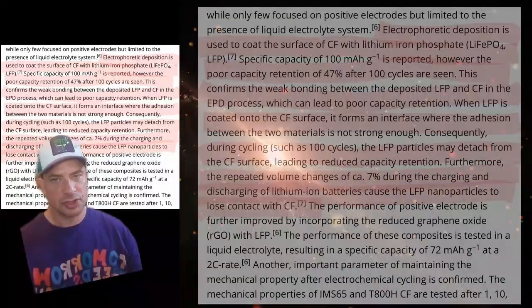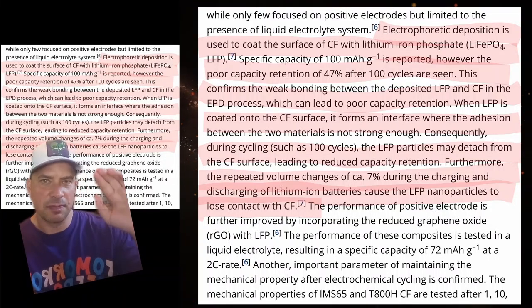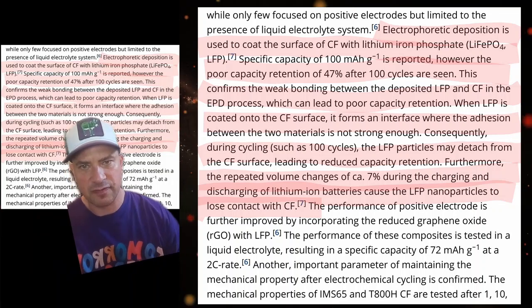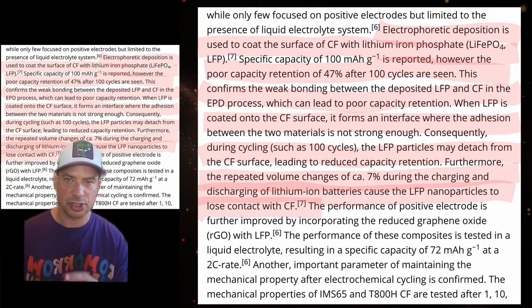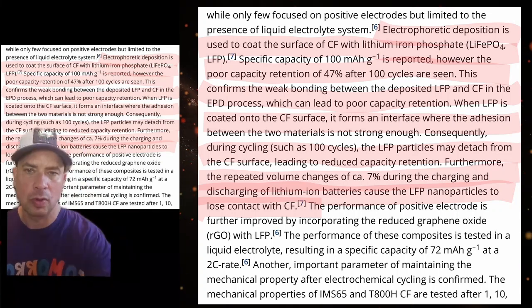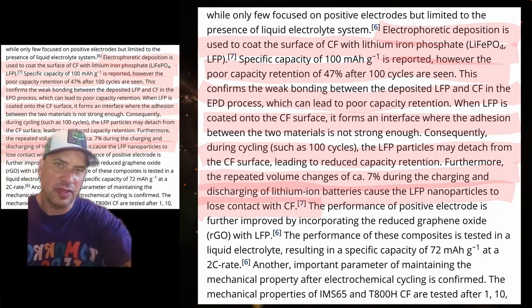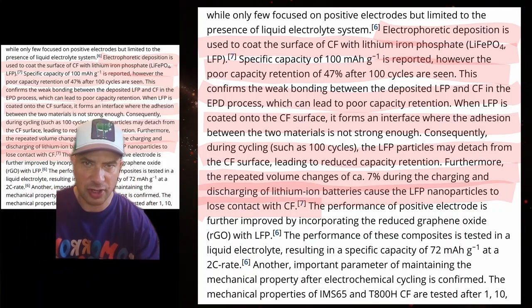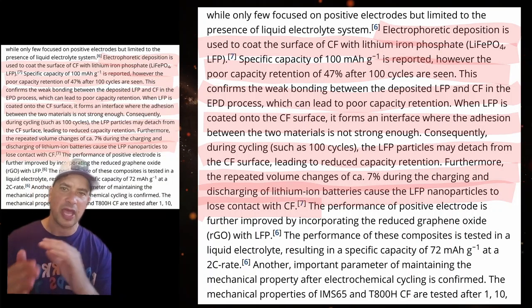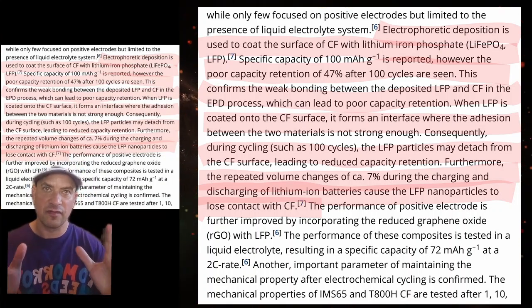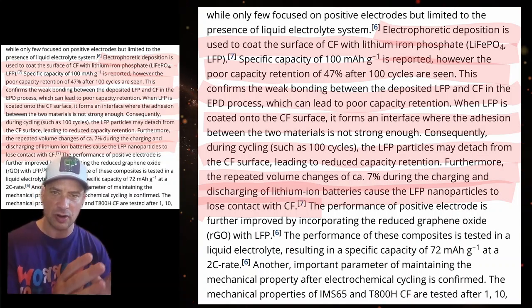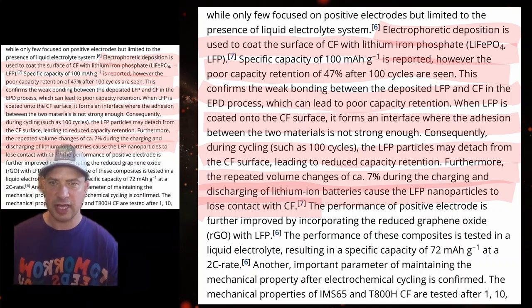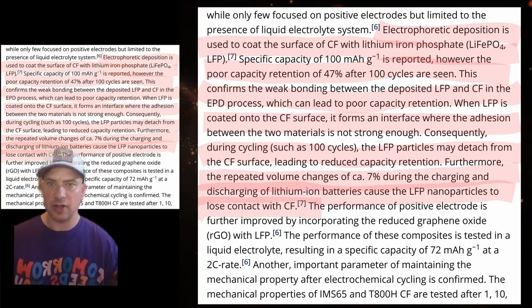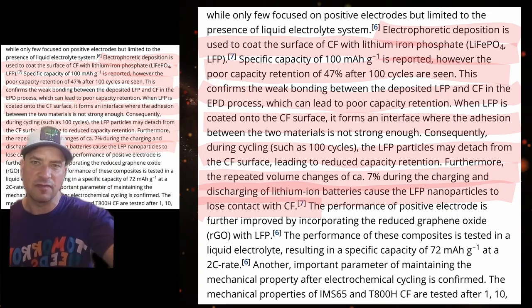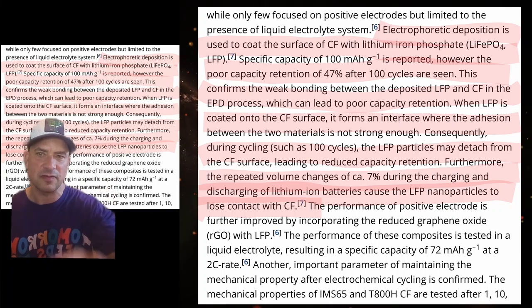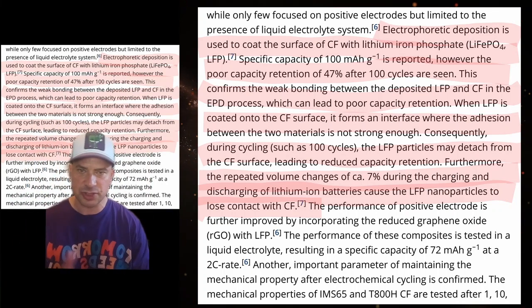to run the vehicle. So a while back, people started having the idea of depositing lithium iron phosphate onto carbon fibers. And then those carbon fibers could be part of the structure of the vehicle while producing power for the vehicle. Well, there was a problem with that. The lithium iron phosphate just wouldn't adhere very well to the carbon fibers. A second problem is that when the power would be discharged from that battery, the volume would shrink somewhat. And then when it would be recharged, the volume would have to go back up. And what this led to was the lithium iron phosphate falling off of those fibers so that they would lose capacity. In fact, they were only retaining 47% of their capacity after 100 cycles of use and recharge.